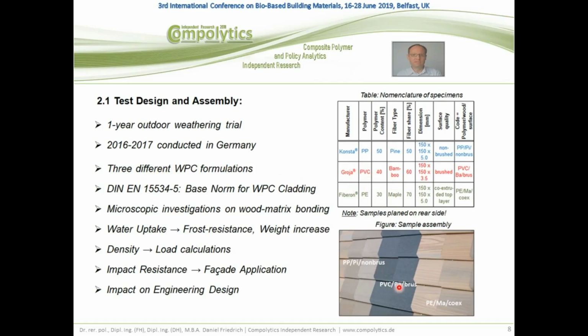They were installed and mounted on a test rack and exposed to the natural weathering on a roof in central Germany, and they were then subjected to such an outdoor weathering trial according to the WPC base norm. Then we did some microscopic investigation about the surface change over this 1 year. We measured the water uptake and density as the physical properties, and in terms of mechanical properties we tested for impact resistance and also modulus of rupture to get more information about impacts on the engineering design.